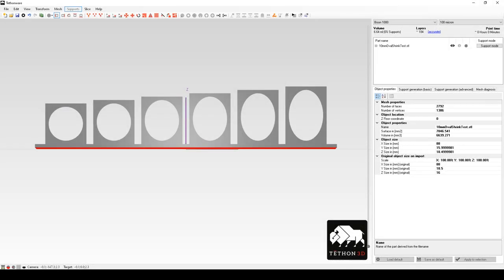Given that many factors can affect how the object shrinks in the kiln, or you may in fact be creating a new material, you will need to find the shrink rate of the material on your own. One way you can find the shrinkage in the Z dimension is by scaling a model incrementally vertically, like you see here.